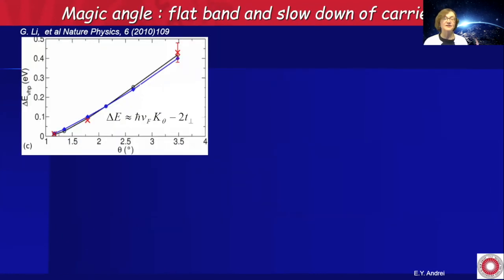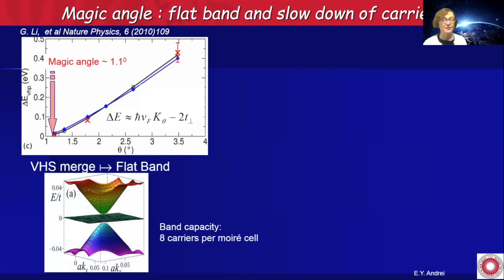So plotting the separation between these Van Hove singularity peaks as a function of twist angle, you reach a point, and that was another surprise at the time, where the separation goes to 0. What this means is that you have a flat band. So your band has become flat here at this magic angle, which is not 0 degrees, but 1.1 degrees. And of course, now this narrow band can take 8 carriers per Moiré cell, because the degrees of freedom are 2 for spin, 2 for layer, and 2 for valley. So 8 carriers per Moiré cell will fill this band.